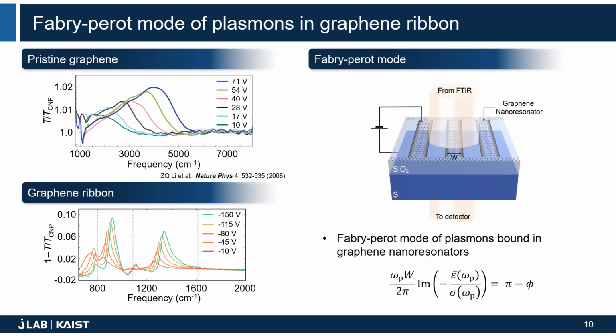However, it's not possible to observe graphene plasmons in the far field using unpatterned graphene. When we illuminate light onto unpatterned graphene, we get very low coupling efficiency. So to overcome this limitation, graphene is patterned into periodic nanoresonators to enhance the coupling efficiency. Then Fabry-Perot modes of plasmons are bounded in graphene nanoresonators. With some assumptions, we can achieve this simple dispersion relation of graphene plasmon.